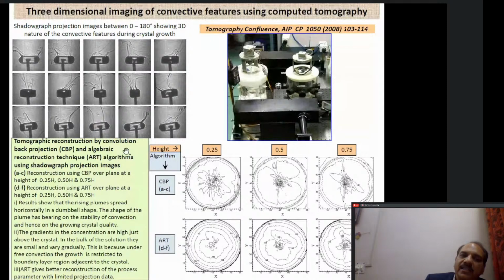convolution back projection and algebraic reconstruction techniques, to find out the 3-dimensional pattern of the convective fields and also of the concentration fields on the surface of the growing crystal at different heights of the crystal. And we were able to show from there how the convective fields spread from the top of the surface when the plume is rising, and how it disappears in the bulk of the solution. So we were able to reconstruct these convection and concentration fields at different heights, 0.25h, 0.5h, and 0.75h. We take the total height as h, and then 75% of that, 50% of that, and 25% of that. And these were the results which we showed for KDP.